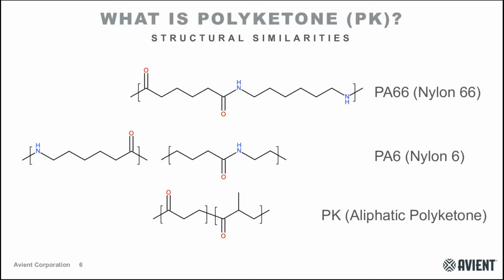Another interesting thing to note about polyketone is it's not a perfectly alternating copolymer of carbon monoxide and ethylene. If you actually have a perfectly alternating copolymer of those two monomers, the material is so highly crystalline that it becomes very difficult to process and use. So as a result, there's a tiny bit of propylene that is copolymerized into the material as a sort of engineering defect that winds up improving the processability. It's one of the unique features of polyketone. This makes the material much more moldable, and Jeremy's going to talk a little bit about that later in the presentation.